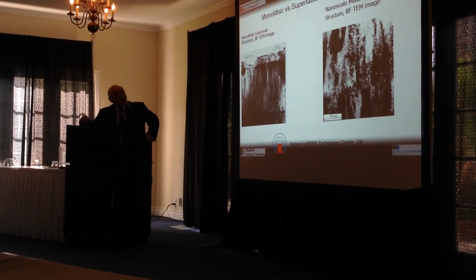It was just the fact that when you go in this range of hardnesses, it is so difficult to be accurate in the measurement. We all know that this is a really dangerous area. This is how a superlattice looks like, multilayers. Compared to the monolithic uniform coating, these are much denser structures. You don't have the columnar growth, the voids.